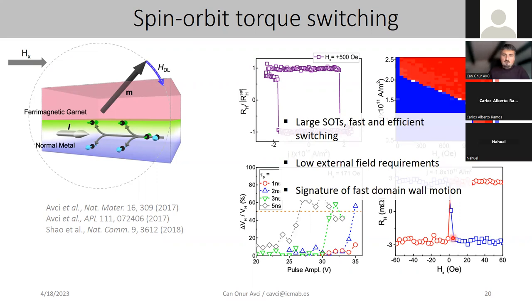So this showed that the fast switching, especially here, was like a signature of very fast moving domain walls, because we know that spin-orbit torque switching is basically domain nucleation and domain wall propagation. So it's not like a single spin switching, but rather you just nucleate a domain and then that propagates with the spin-orbit torque. So based on some calculations, we said that the domain wall motion should be very effective in these films.